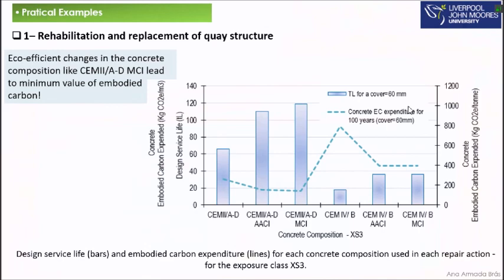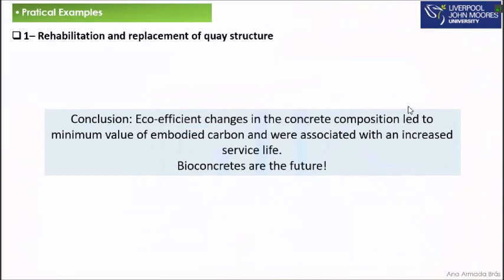Okay, so we know that eco-efficient changes in the concrete composition, like cement 2, lead to minimum value of embodied carbon. So what is the main conclusion? The main conclusion is that eco-efficient changes in the concrete composition led to minimum value of embodied carbon and were associated with an increased service life. So it seems that development of biocomposites, in this situation bioconcretes, are a possible solution for this problem.